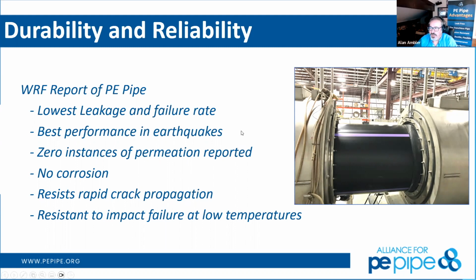No corrosion does resist rapid crack propagation, and essentially rapid crack propagation is an impingement or a failure within the pipe running across a fused joint. The advanced resin of the 4710s and above have all solved for that rapid crack propagation, to stop that and restrain that from running across fused joints as we go through that.